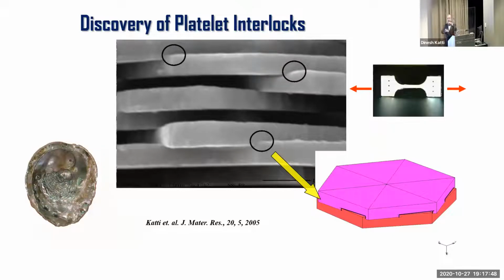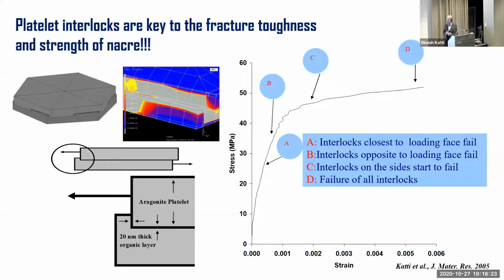What we saw was that these bricks were not just sitting one over another like a brick wall, but each brick was locked into the other brick. So the circles here show you how the bricks are locked into each other. Now, we wanted to be certain that this is the reason for fracture toughness. So we spent a year building models of these interlocks. And then we did our simulations. And what we found is that because of the progressive failure of these millions of interlocks in this nacre, we get this very high fracture toughness.